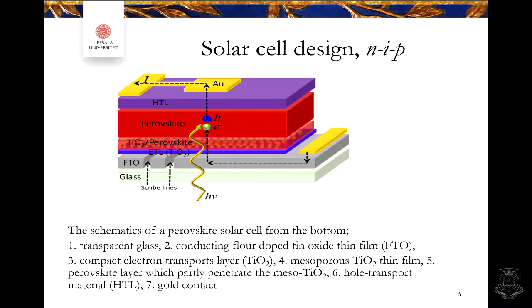So here you see this is the electron conductive materials. First we have a transparent glass, transparent fluorine-doped tin oxide. Then in this case there is TiO2, titanium dioxide, and a mesoporous titanium dioxide layer, then the perovskite, then the hole transport material. Many times the material that is used is spiro, which transports the holes, and then in this case here is some gold. So this is how a solar cell is built up.